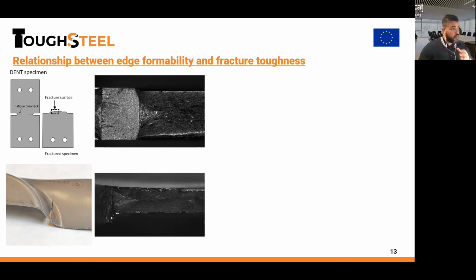Actually, if we take a closer look at the fracture surface of a pre-cracked specimen, like the one that we use for fracture toughness testing, and compare it with the fracture surface of a sheared edge, an edge fracture, we can observe certain similarities between them. For example, the formation of this triangle zone or flat zone at the beginning of the crack initiation and the transition to a more slant fracture of 45 degrees.